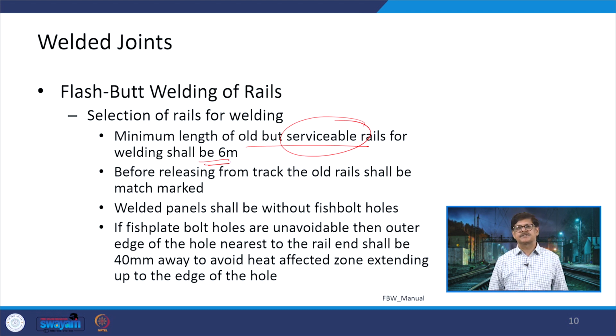If it is less than 6 meters, it should not be used for the welding. Before releasing from the track, the older rails shall be match marked. The same thing as we discussed in the 80 weld. You have to look at that if this is a rail and this another rail. So, if it is left side rail, inner side, outer side.